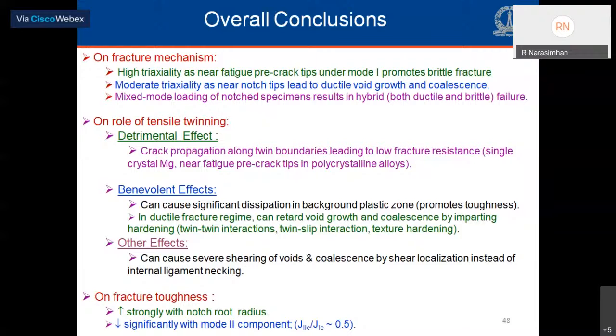And we were able to understand this by examining again the microstructure, which plays the most important role as far as magnesium alloys are concerned. It shows that again twinning is one of the most important factors affecting both the fracture mechanism as well as the possible dissipation in the background plastic zone.